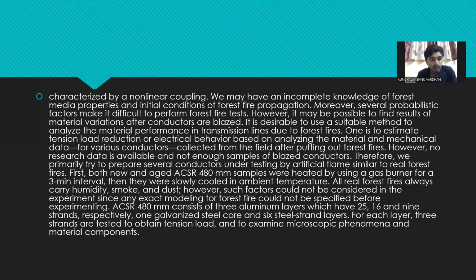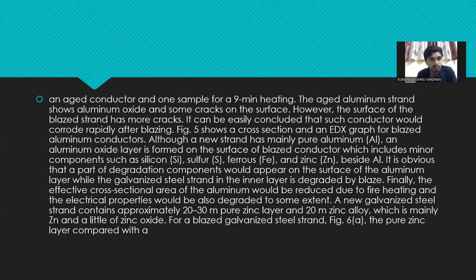before experimenting. ACSR 480 consists of three aluminum layers which have 25, 16, and 9 strands respectively, one galvanized steel core, and six steel layers. For each layer, three strands are tested to obtain tension load and to examine microscopic phenomena and material components. An aged conductor and a sample for a 9-minute heating.